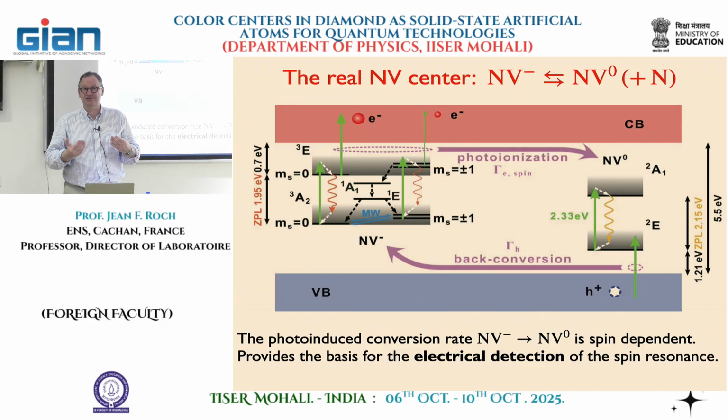And the consequence associated to a short T1 is that the intensity of luminescence of the NV will be drastically modified, will be much shorter also. So just by looking at the brightness of the emitter, you can see whether or not there is the existence of a strong transverse field. It's hardly quantitative. It can be a little bit quantitative, but the good point is, if you just do a mapping and you want to measure, for instance, a domain wall associated to a magnetization that goes from that to that, there will be a transverse magnetization at that point, and this transverse magnetization can induce this, you can observe it.